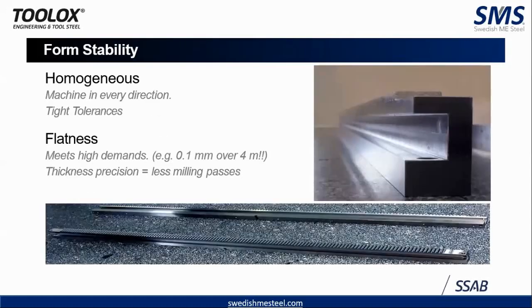So what you got? You got a material which is extremely stable, which is homogeneous. So you need not do machining in any particular direction. In any direction, it's possible to machine the block. It can achieve extremely high demands in flatness, up to 0.1 mm over a 4-meter length, which is precise.